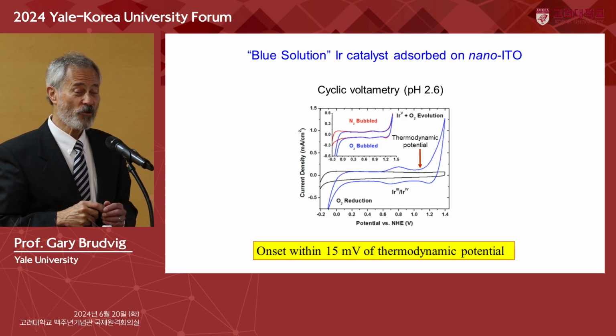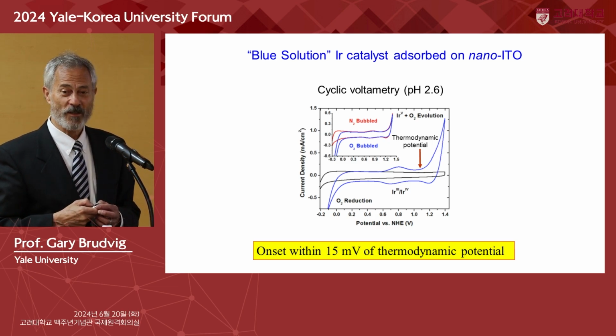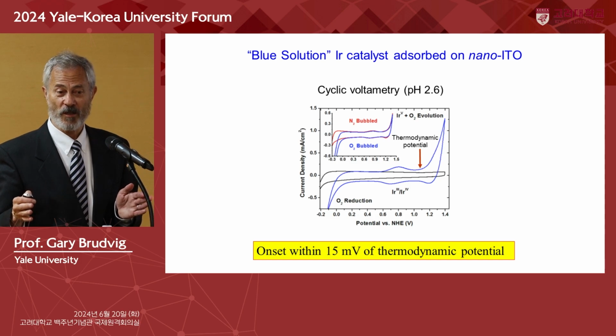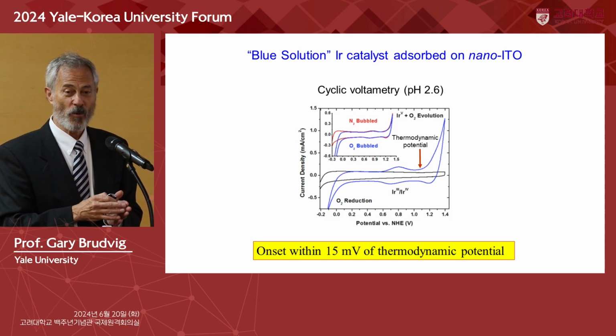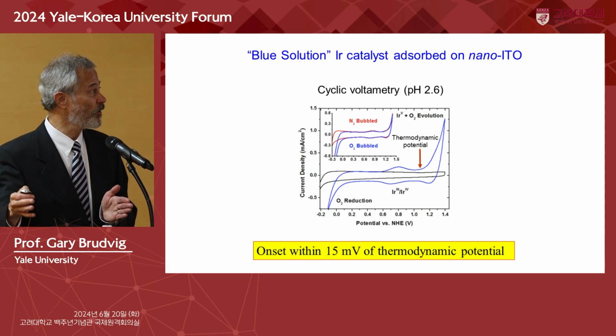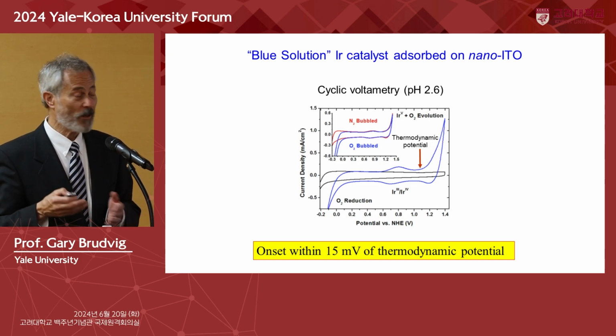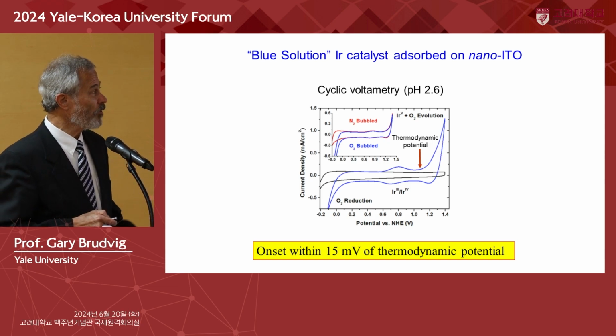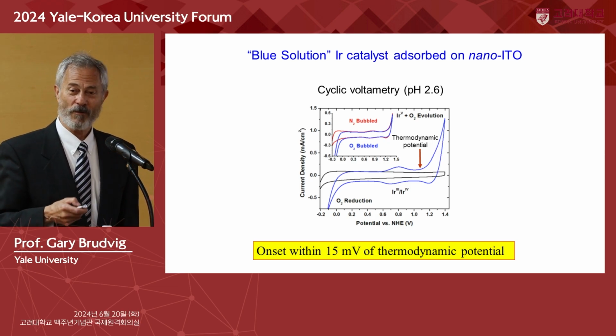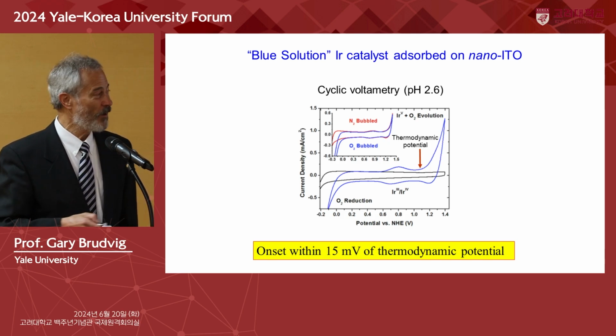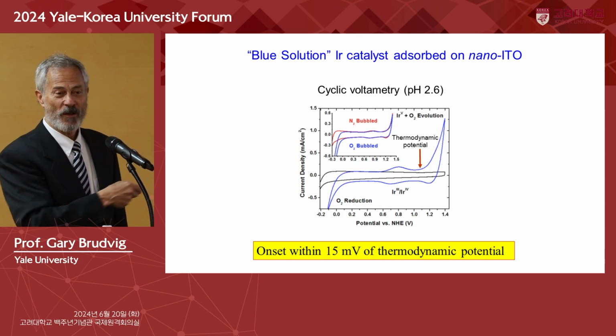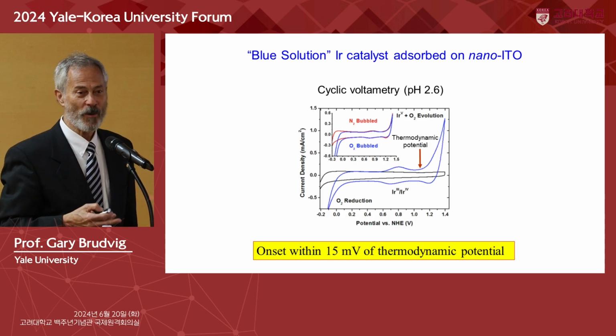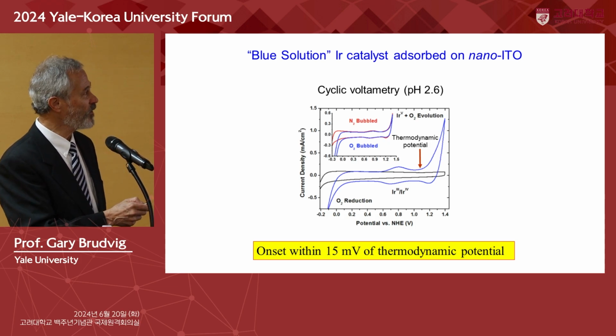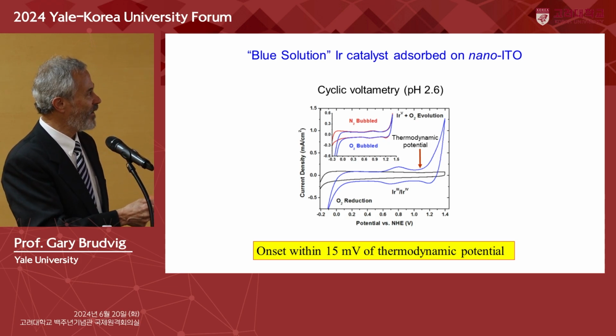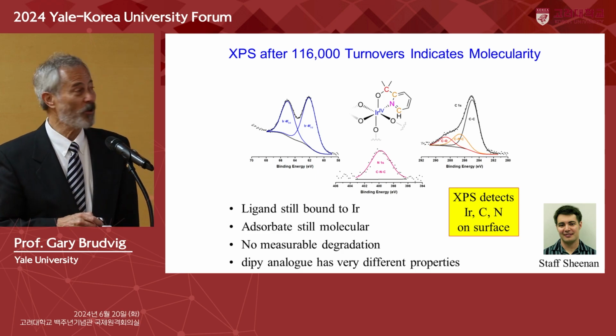So normally when you do catalysis of water oxidation, there's a very large overpotential, and it's the voltage that you require above the thermodynamic voltage to do the reaction to make it go fast enough. Typical overpotentials are on the order of 400 millivolts or so, and here we see an onset within 15 millivolts. This is the very best that has been achieved, and it's completely stable.